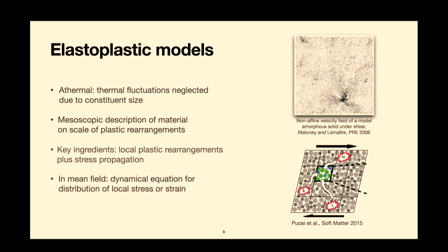So based on that, you can build a simpler kind of model, which are coarse-grained, and they're called elastoplastic models. Okay. In their simplest form, they are athermal, which is the regime anyway that we're looking at. So we ignore thermal fluctuations, and it's a mesoscopic model in the sense that, this is a nice sketch from a paper by Puosi et al., you partition the system schematically into blocks, and you look at each block and try and characterize that not specifically by what the particle arrangement is, but just macroscopic variables like strain or stress. Okay? And so the key ingredient in these elastoplastic models is basically, of course, changes due to the mechanical driving plus these plastic rearrangements that I mentioned, okay?